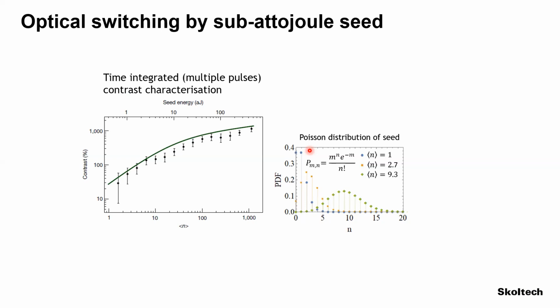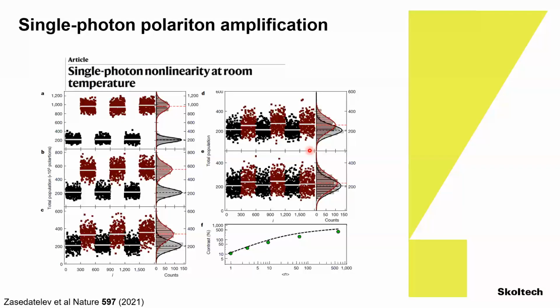For every pulse of light that we send, and these are femtosecond pulses, for every pulse of light that we send on the structure, we can do the full spectroscopy. We can measure the dispersion, we can measure the coherence, and we can also accurately characterize the intensity of the beam before it reaches the sample. And here you can see with the black dots the emission from the spontaneously formed condensate, and with the red dots the emission when we seed with some particular energy, with a certain number of photons. And each dot that you see is a realization of this condensation or amplification process.